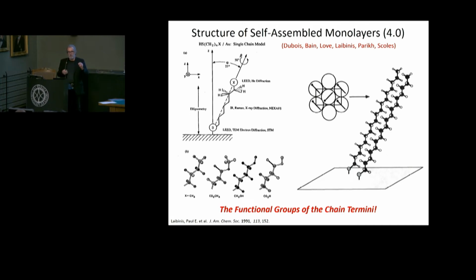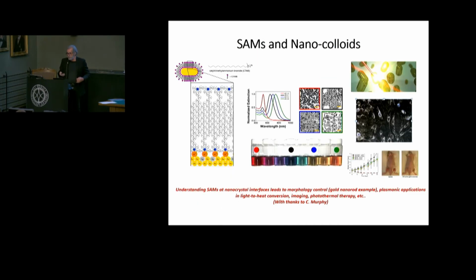And to actually show, for example, thermal behaviors that correspond to how these layers melt when you have a canted structure. They're tilting because the lattice spacing is larger than the dimensions of the chain, and so the chains tilt to maximize their lateral interactions. And when you heat them up, they melt, but they don't melt uniformly. They melt from the top down. This is confirmed by really complex measurements such as helium diffraction and LEED measurements, but also by theory done by Michael Klein, and a really beautiful story emerged. The underlying motivation original to this work was to have these ambient functional groups not just be low surface free energy things like methyl groups, but rather a much more articulated set of functional interactions. So that's the part of the story I want to turn to now.